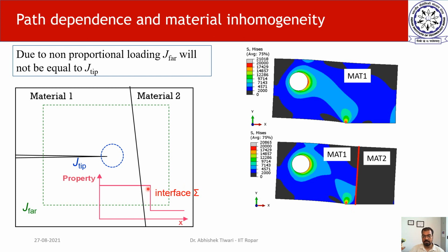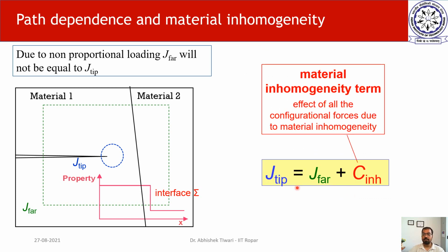If the material 2 has higher Young's modulus, then reverse will happen and less energy will be available. So under such conditions, J tip is not equal to J far, but there is an additional term. Whether or not it is positive or negative depends upon what kind of transition it is. If it is hard to soft transition, C inhomogeneity term is negative. That means J tip will be having more value. So C inhomogeneity term will be positive, and reverse would happen if it is soft to hard transition.